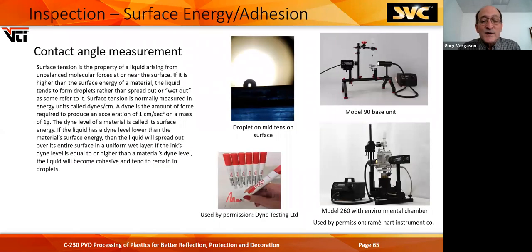So how do you do that? You have your substrate. You put a drop of liquid on there, and you put a little backlight behind it, and you look at it. And if this is a very high surface energy, this drop will be really flat. If it's very low surface energy, the drop will have more energy than the surface, and the drop will look like a BB sitting on the surface. You can use dyne pens, different dyne levels, which Dyne Testing Limited over in England makes.